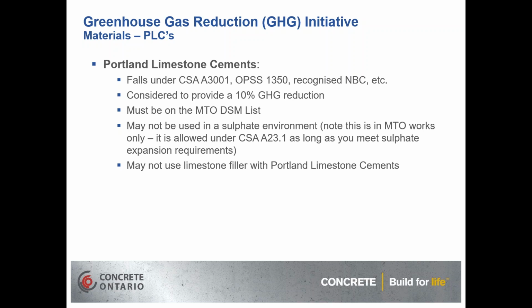Now, Portland limestone cements, the specifications on that, they fall under CSA A3001, OPSS 1350. It's recognized by the National Building Code, and it's been well accepted in Canada. And we are considering that the Portland limestone cements provide us with a 10% greenhouse gas reduction, because instead of incorporating 5% limestone like we would in a conventional Portland cement, we're going to be incorporating around 15%. So that's where we're getting that 10% greenhouse gas reduction number.